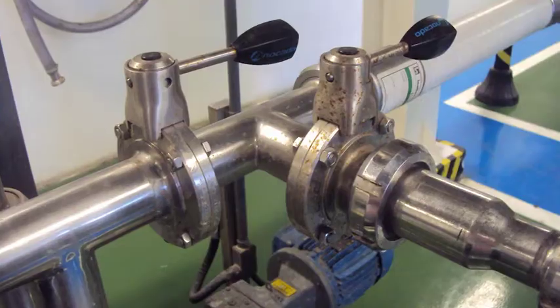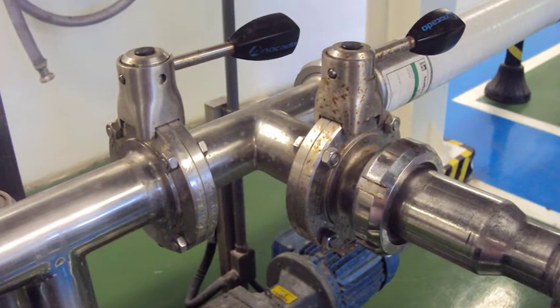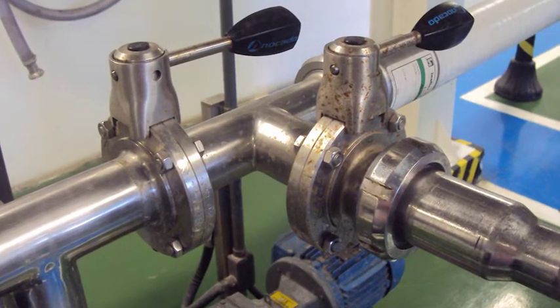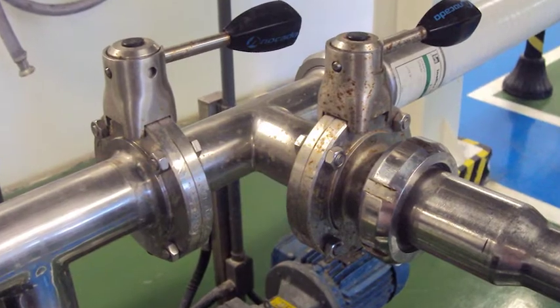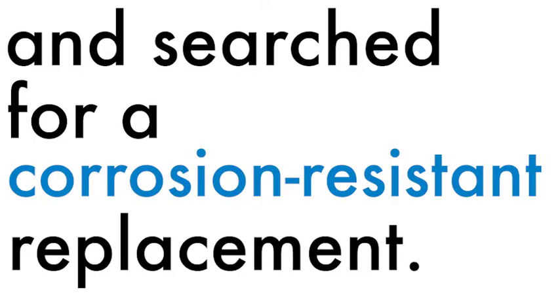Unfortunately, less than 9 months later, the facility noticed more corrosion, and poor quality was blamed once again. More corrosion was detected less than 3 months after the third replacement was installed, and the company finally determined that 316L was not suitable for their process and searched for a corrosion-resistant replacement.